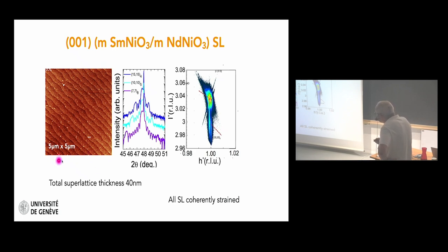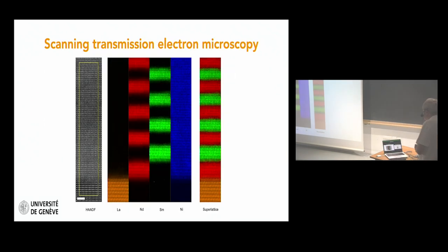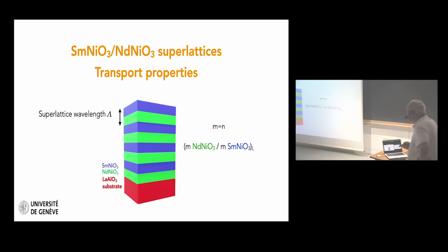This is the surface of the samples. It's atomically flat, so you have atomically flat terraces with one unit cell step height. These steps are linked to the miscut of the substrate. X-ray diffraction shown here shows these fringes, which are a sign of the finite number of cells, and additional peaks that you see here, which are linked to the artificial modulation of the length. And this reciprocal space map is simply showing that the films are coherent. There are no dislocations at interfaces. Scanning transmission electron microscopy shows also, I'll come back to this image a little later, that the layers are very well defined.